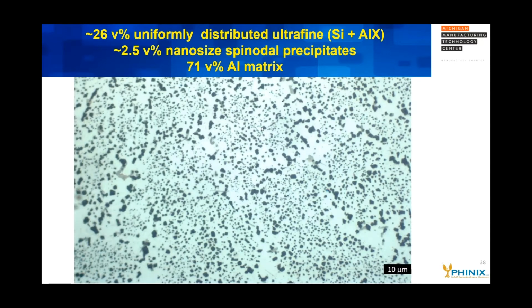This is our target. This is our material that has been already made on the lab scale. It has 26 volume% of pretty uniformly distributed ultrafine silicon, and there is a little bit of residual intermetallic, all isolated. There is also 2.5 volume% of nano-size spinodal precipitates in the aluminum matrix, strengthening the whole thing.